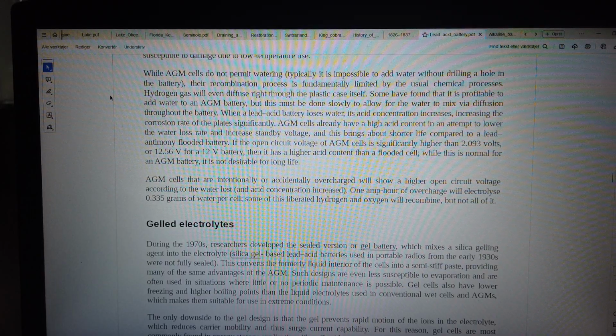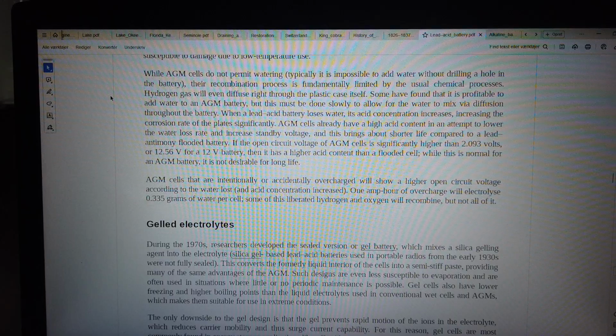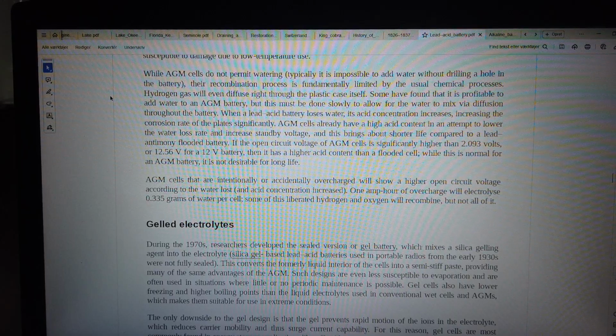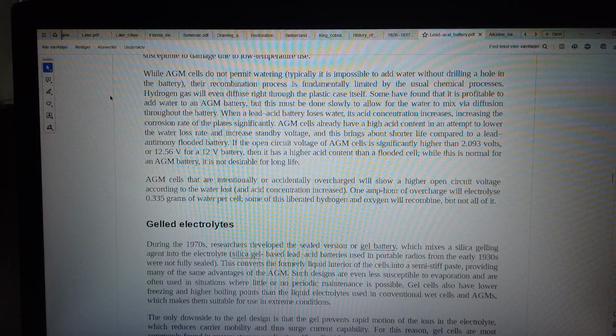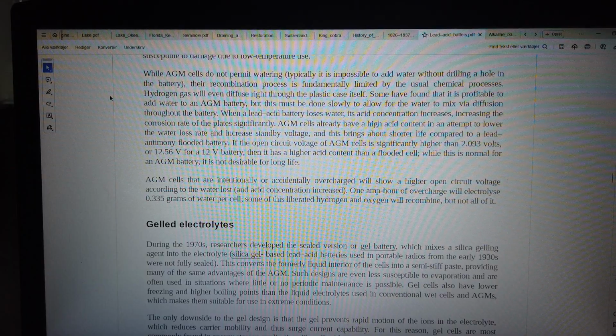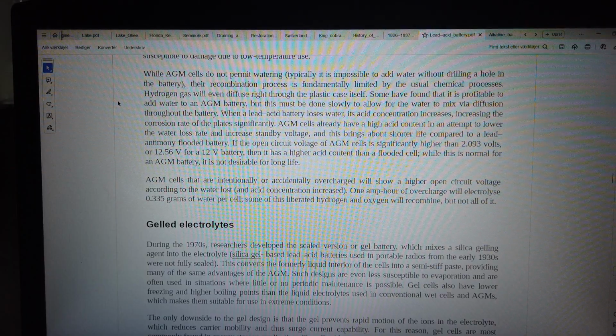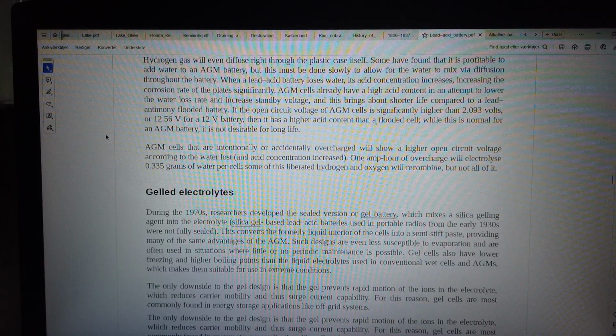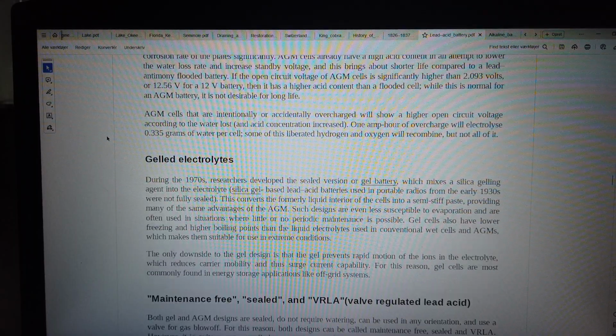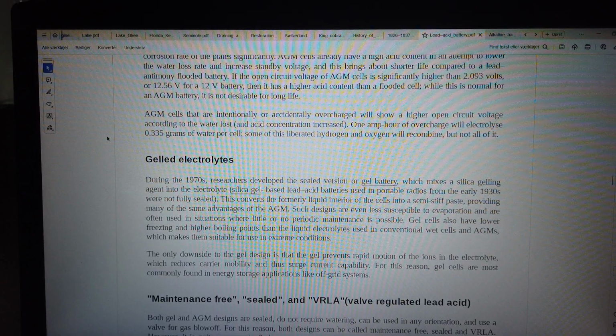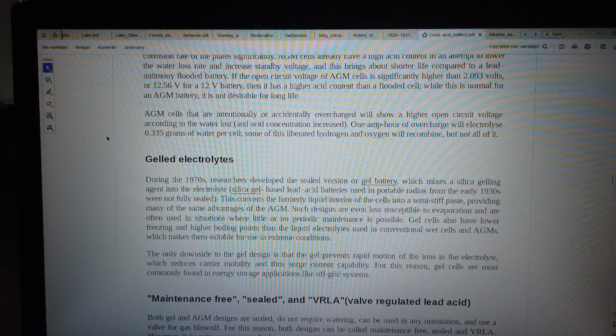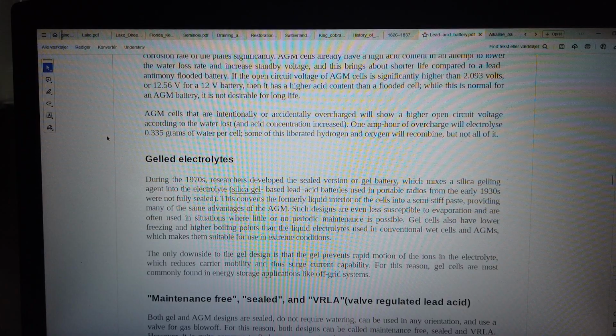When a lead acid battery loses water, its acid concentration increases, increasing the corrosion rate of the plates significantly. AGM cells already have a high acid content in an attempt to lower the water loss rate and increase standby voltage, and this brings about shorter life compared to a lead antimony flooded battery. If the open circuit voltage of AGM cells is significantly higher than 2.093 volts, or 12.56 V for a 12V battery, then it has a higher acid content than a flooded cell. While this is normal for an AGM battery, it is not desirable for long life.